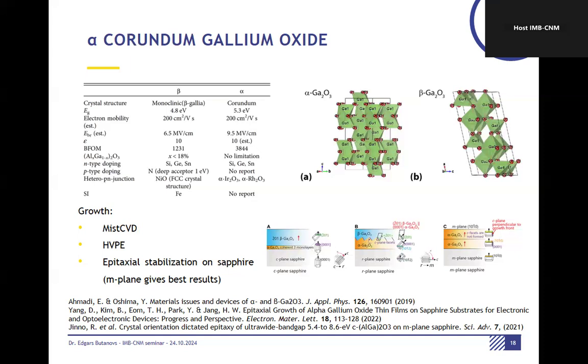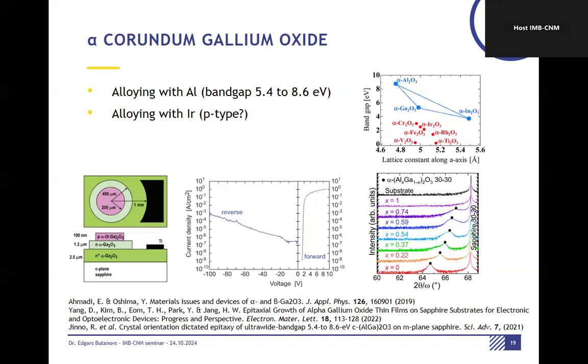I will talk a bit more about our results as well, so there'll be more details. What other benefits there are of alpha phase gallium oxide is, first of all, alloying with aluminum. If we want to alloy the thermodynamically stable monoclinic phase, there's quite a big limitation. You can go up to like 25% or something until it gets very bad, to say the least.